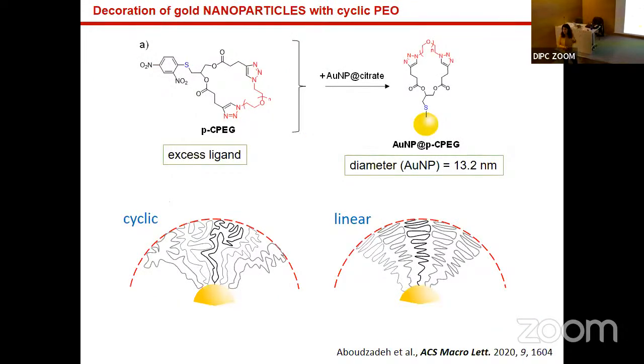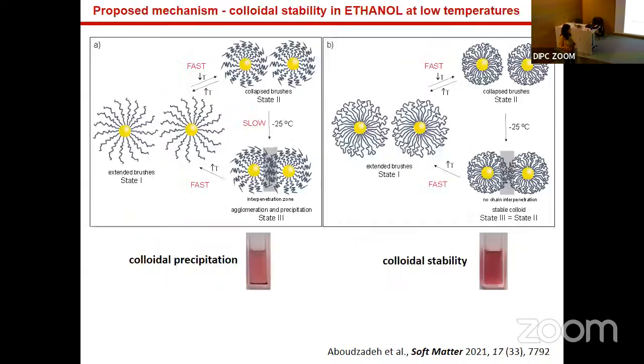Then we went to the nanoparticles, and with the same experiments, we used the same polymer by a ligand exchange protocol, and we observed differences in the colloidal properties with the temperature, with the presence of ions, etc. And if you look at the picture, you can imagine. So I drew here 5 chains, 5 and 5. But if you see here, the density of chains near the surface is much higher than here, because two parts of the chain have to be connected to the gold. And this increase in the concentration of chains near the surface has an implication on the colloidal properties of these nanoparticles.